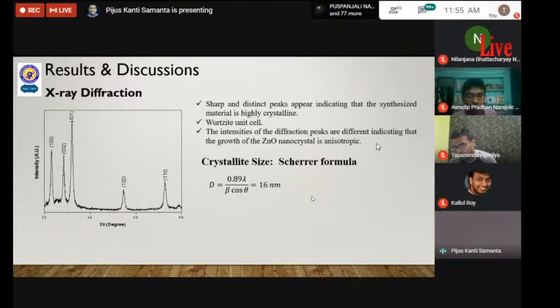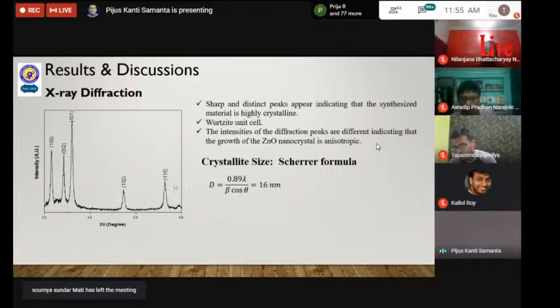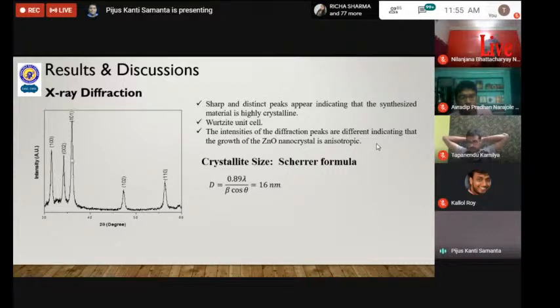The structural studies involved the X-ray diffraction studies, and here it shows the X-ray diffraction pattern of the synthesized material. Sharp peaks appeared over here that indicates the good crystallinity of the material, and we have indexed these peaks and found the structure to be hexagonal, and these peaks indexing is quite consistent with the standard JCPDS. And from the diffraction curve, we can also calculate the crystallite size.